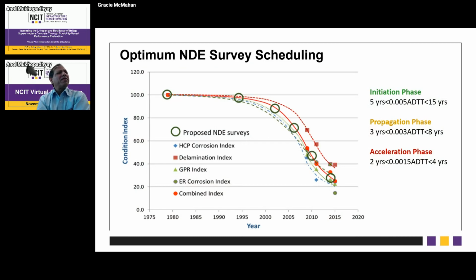Okay, see here, they actually developed the model and predictive capability based on the NDT evaluation. They did a particular bridge from 2009 to 2015, around a 6-year time span, and there are 4 data points. This kind of evaluation is necessary. And you see there are individual curves for half-cell potential, delamination, GPR, and there is a combined condition index curve over time. You see that this is all in an acceleration phase. So your corrosion potential is pretty high, and the combined index is going on, and they try to fit those 4 points. They try to develop a sigmoidal curve, but of course the beginning values are not available.